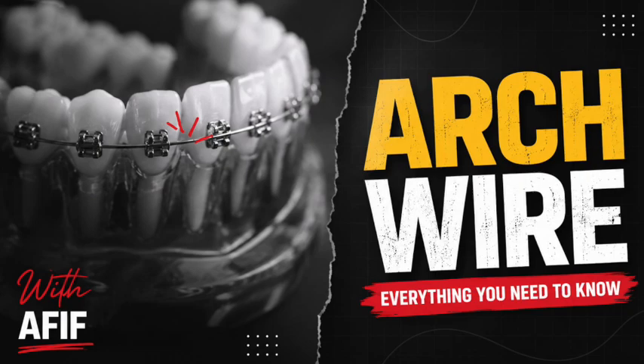No, it doesn't. Because this phase shift, this jump between austenite and martensite, isn't just triggered by mechanical stress, right? Correct. It's also uniquely sensitive to thermal energy. Heat and cold. Which brings us to the concept of thermoelasticity, or wires with a memory. Yes. While superelasticity is the phase shift triggered by mechanical stress, there is a sister phenomenon inherent to nitinol known as shape memory, or thermoelasticity. Memory. This is the transition between the martensite and austenite crystal structures triggered entirely by changes in temperature.